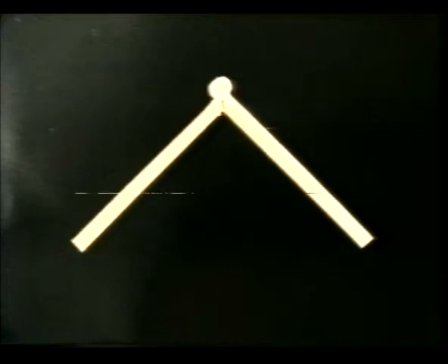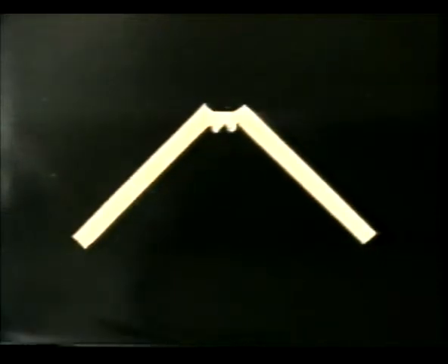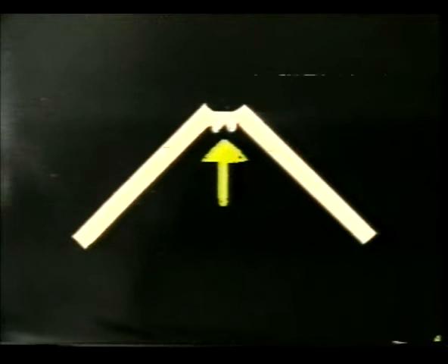Now if you have the gap too small, you'll get the weld bead sitting on the outside corner, leaving you with a rather weak joint. Alternatively, if you have the gap too wide, the metal will sag through at this point, leaving you with a really overcooked weld, and it will be brittle. So this is another good weld to practice on, and this is what it will look like underneath.